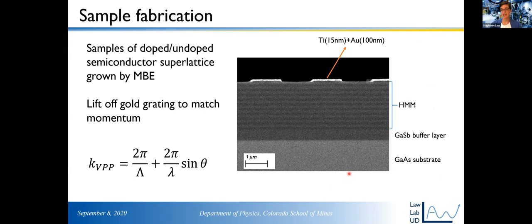So we wanted to see if we could actually make these and if we could actually see them in our semiconductor hyperbolic metamaterials. I'm going to try to speed up a little bit because I think I'm going too slowly. But essentially what we did is we grew this metamaterial. You can actually see the metal layers are darker here in the SEM. These are the doped layers. These are the undoped layers. I actually hadn't expected to see this. I was pretty excited. And then we put a gold grating on top. We have to put the gold grating on top because remember, the momentum of these volume plasmon polariton modes is huge. It's much larger than the momentum of light in free space. So we have to do something to match the momentum, and a grating coupler is the easiest way to do it.